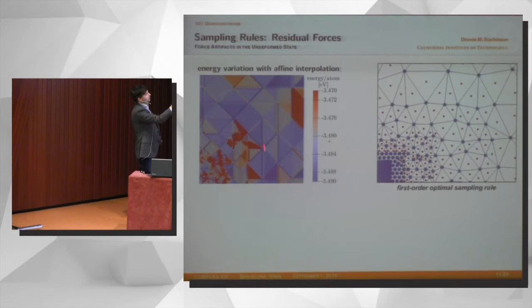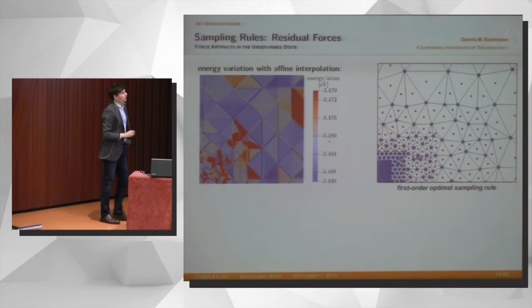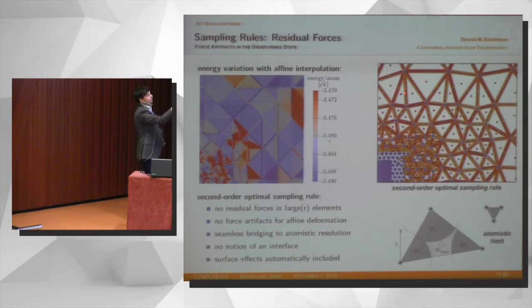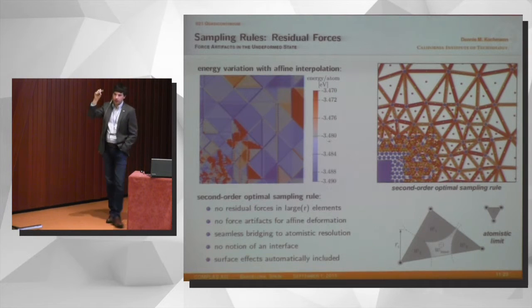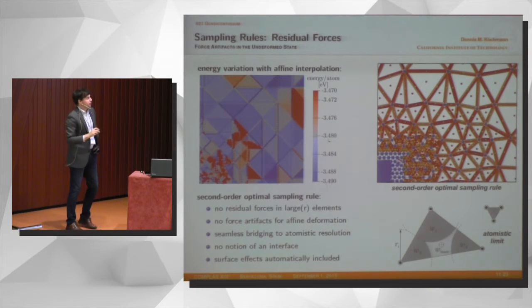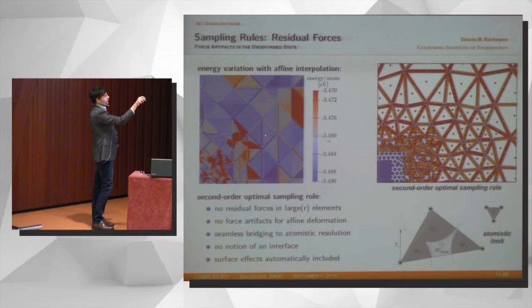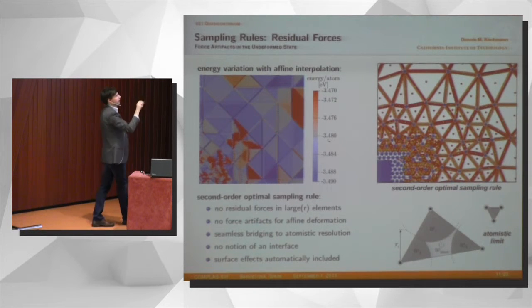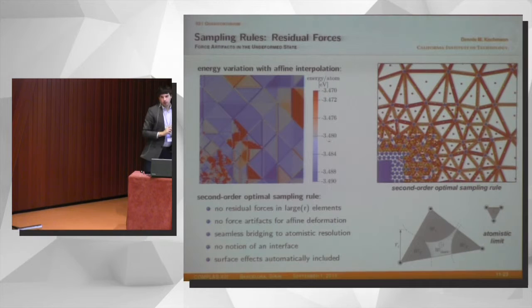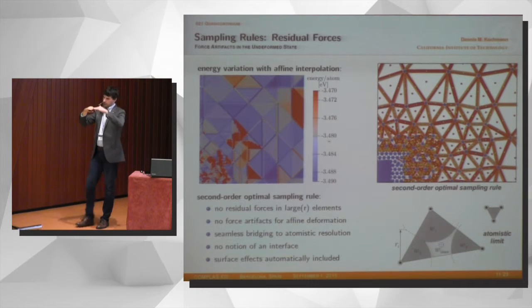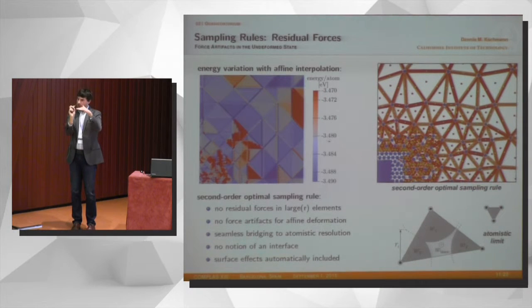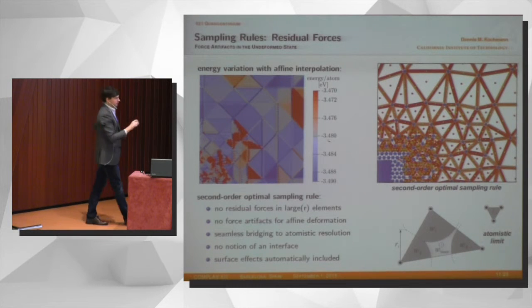Now, of course, you can argue near the edges, you also see differences. So why not introduce a second-order scheme, which has additional quadrature points on the actual faces of the elements? And by doing this, we take into account the constant energy of the inside, the changes on the faces and on the nodes. And by the way, this also works beautifully for surfaces, because if you have a free surface, you're putting one sampling quadrature type atom on the surface, so you actually feel the surface interaction as well.